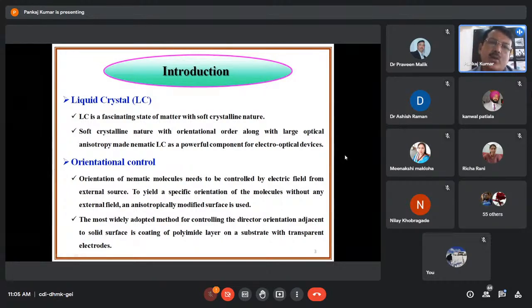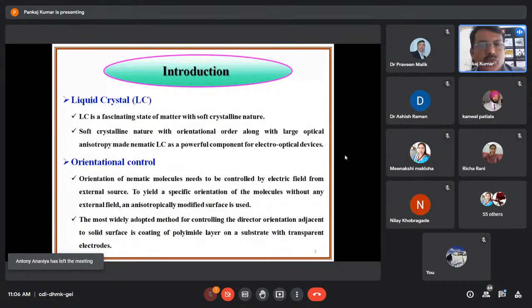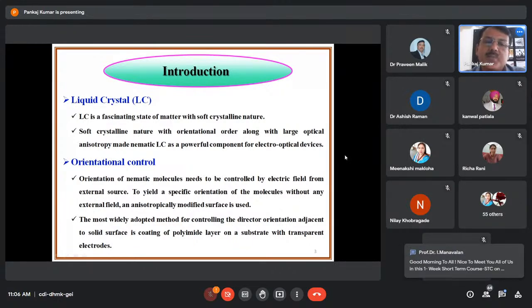So orientational control is an important parameter for any display device. The orientation of nematic molecules needs to be controlled by an electric field from an external source, to yield a specific orientation of the molecules without any external field, and an anisotropically modified surface is used. The most widely adopted method for controlling the director orientation adjacent to a solid surface is a coating of polyimide layer on a substrate with transparent electrodes.